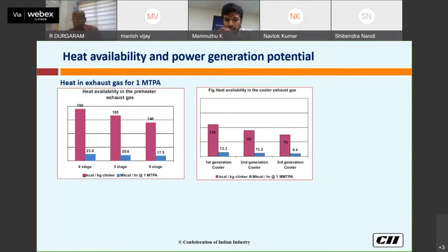So the preheater gas usage is mainly based on the raw mill moisture. If you have more moisture, we have to utilize it for drying, or otherwise you can use it for power generation. And on the clinker cooler side, if we consider a third generation cooler for 1 million ton per annum clinker generation, we will have a heat content of around 9.4 kilocalorie.